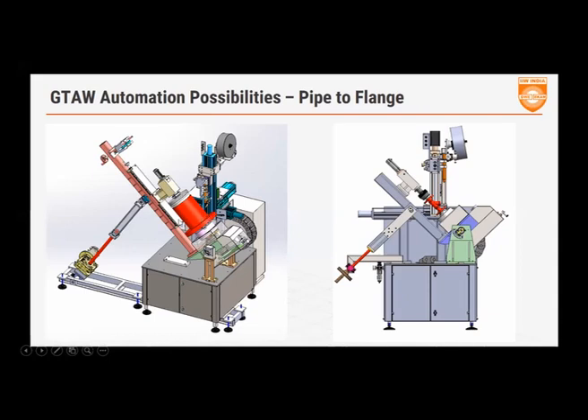Now, if you have welded this in a 1G position and the torch was at 45 degrees, any mismatch or any gap which was inconsistent between the pipe and the flange would reflect in 2 dimensions, the X and Y axis both. When I'm moving it 45 degrees, any mismatch is in the Z axis only, and my AVC can take care of that particular mismatch by reaching closer to the joint.